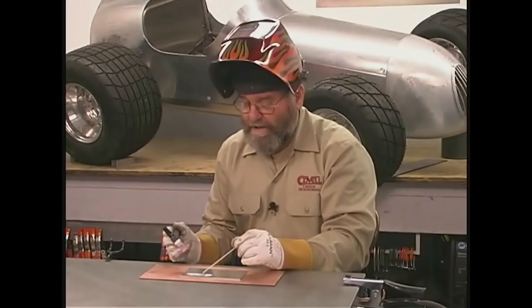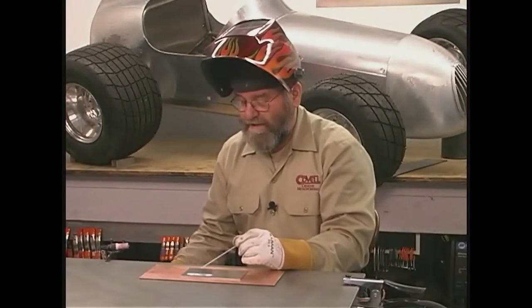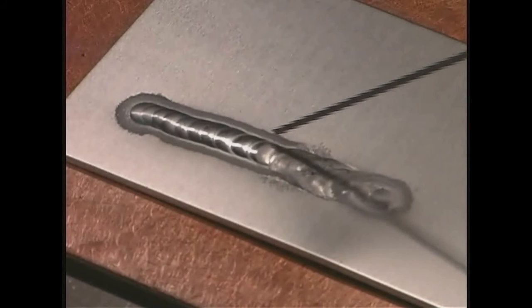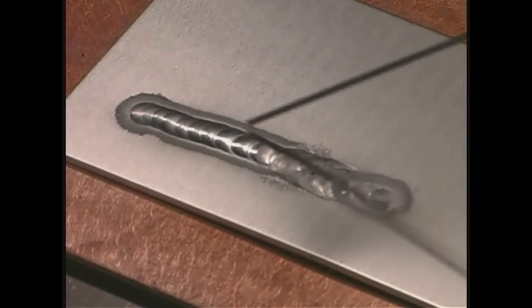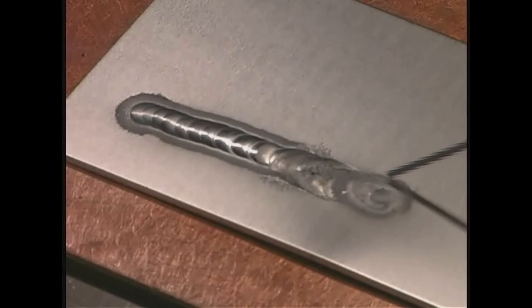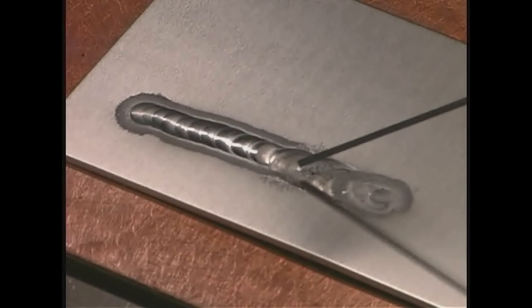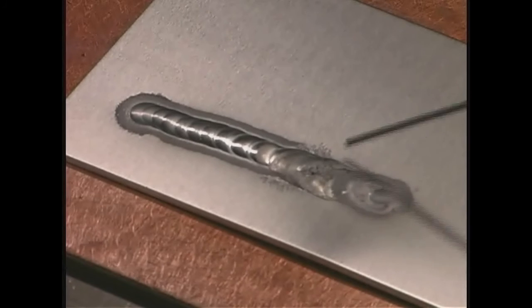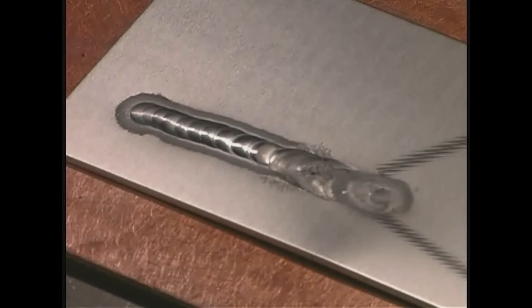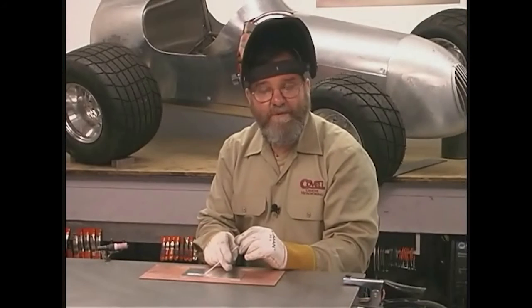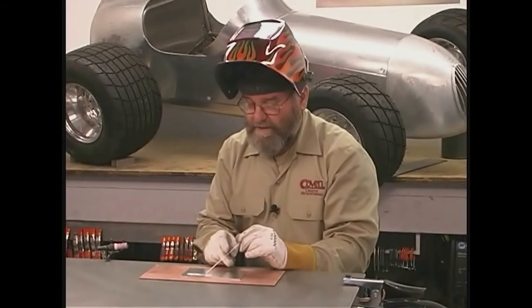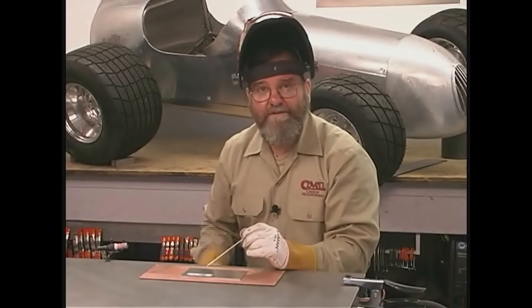Okay, so we'll take a close look at this, and you can clearly see that the first portion of the weld looks very nice. There's a well-defined bead, and in the area where I had the tungsten too far away, the bead has gotten much wider and it's flattened out, and there's not good definition of the weld bead itself. So that's the problem with holding the tungsten electrode too far from the metal.